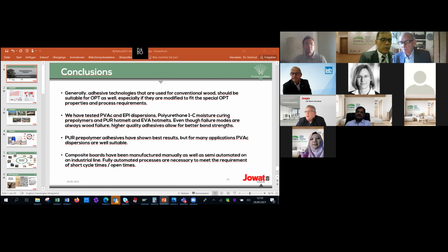And even though failure mode is always wood failure, it is known that the wood is less strong, at least with medium densities, but also parts with the higher densities, less strong than, for example, beech wood. But even though you have always wood failure, you can choose adhesives that have this wood failure at much better bond strength than with other adhesives. So you need to choose the right adhesive for the right performance, for the right product you want to make.